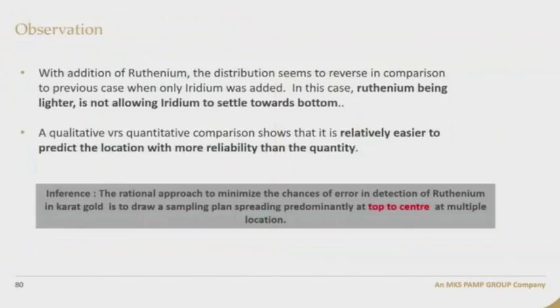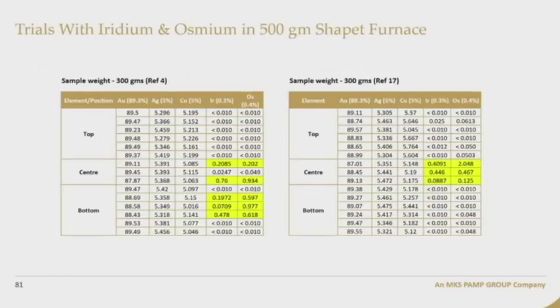So what do we conclude? With addition of ruthenium, the distribution seemed to reverse in comparison to the previous case when only iridium was added. In this case, ruthenium being lighter is not allowing iridium to settle to the bottom. So whenever there's an alloy and we are able to detect iridium and ruthenium, our sampling plan should spread from top to center. More analysis should be done at the top surface.